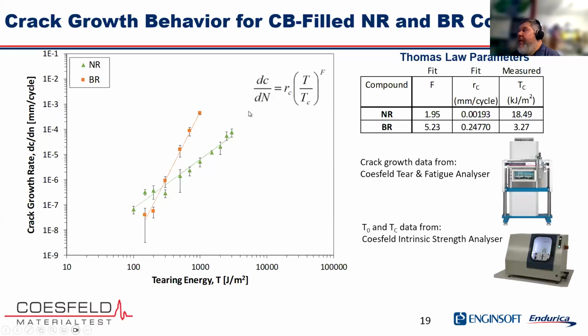So now the data set I'm showing you here is from a full-blown crack growth test that we run on a servo hydraulic machine. In this case, this was run with the tear and fatigue analyzer from Coesfeld. This test takes about 20 hours to collect this data set. Now, again, when you're a materials person, a lot of times you want to screen large numbers of candidate materials, and if your test takes a whole day, that's inconvenient. So one of the really nice things about this intrinsic strength type of test is, again, it executes rather quickly. And in this test, you measure the fatigue limit.